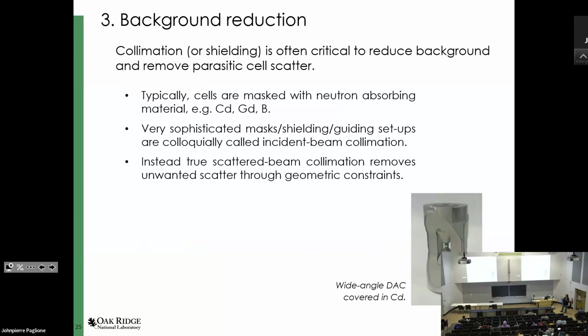So typically what you do in most cases is you wrap everything you don't want exposed to the beam with cadmium. So here you see an example of a diamond anvil cell where all this gray stuff, with the exception of the anvils and the gasket here, is cadmium. So this already reduces the background a lot. But as your samples get smaller and smaller, your pressure cells also change in geometry as you apply pressure, so there's a limit to how much you can achieve with cadmium. Aside from the fact that the higher energies at a spallation neutron source will actually penetrate cadmium. It's not applicable everywhere. So we have started,